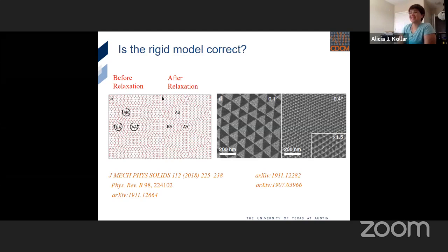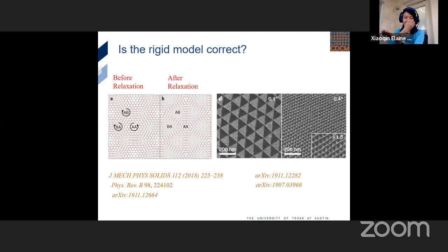So let me show one more slide. Actually, the picture I showed you, with a continuous variation of atoms, is a simplification. In some cases you can have distortion because of strain, and then instead of having these hexagonal lattices, you would have this triangular symmetry. With this triangular symmetry, you have perfect alignment of the atoms, and then they're separated by a wall that's a different alignment. So this is a situation where if you ask, can I have a square well? The answer is yes. In these lattices with lattice relaxation, you have one area where atoms are perfectly aligned, then they relax their energy through a sharp boundary of a different atomic alignment. This situation can be found in the Moiré crystal as well. So there's your square well model.